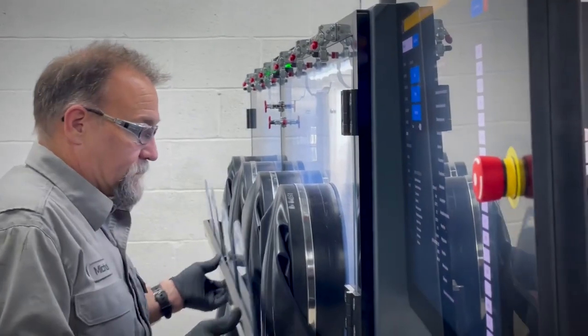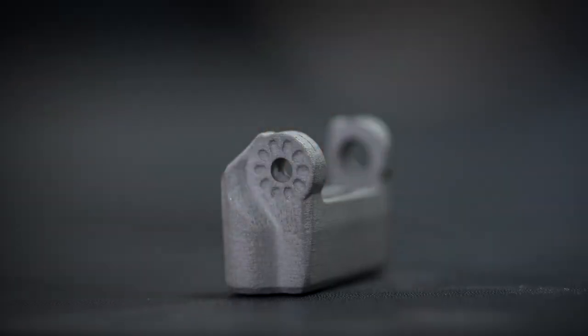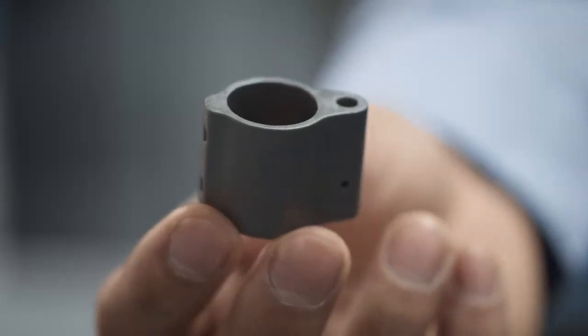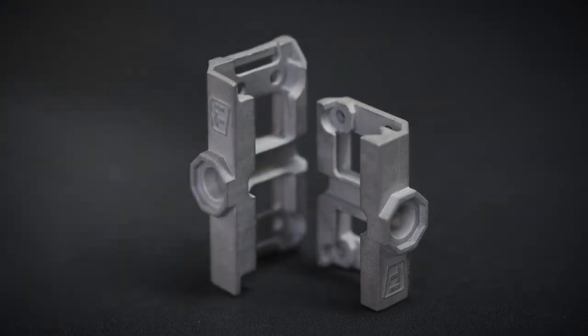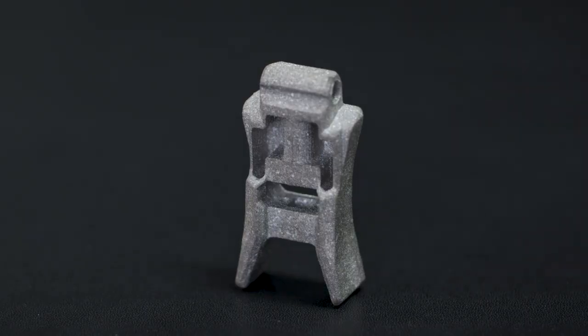The desktop unit, which we have, the P1 production unit, is very good at achieving fine details of complex parts. The P1 has allowed us to achieve some of the best surface finish we've ever seen on an additive manufactured part. We're achieving in the three micron RA or lower range on almost all features.